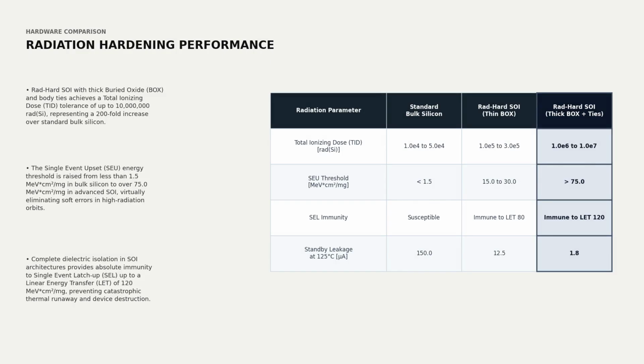Standard bulk silicon cannot survive the intense radiation of low Earth orbit. Space-based defense assets require specialized silicon-on-insulator substrates to prevent catastrophic failure. Advanced silicon-on-insulator wafers with thick buried oxide layers increase total ionizing dose tolerance to 10 million rads. This represents a 200-fold increase over standard bulk silicon. Dielectric isolation also raises the single event upset threshold to over 75.0 units. This design eliminates parasitic paths, providing absolute immunity to single event latch-ups. These physical performance advantages make specialized silicon-on-insulator substrates completely non-substitutable for national security space programs.